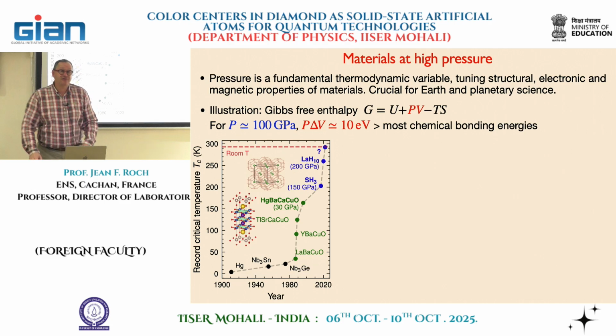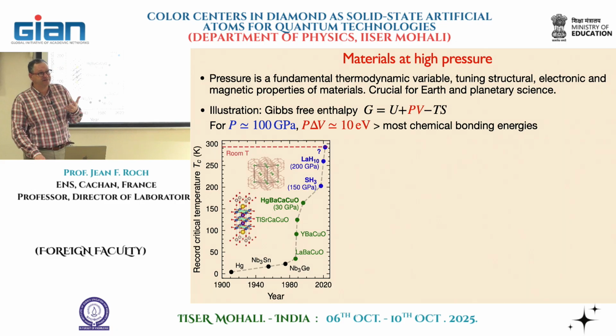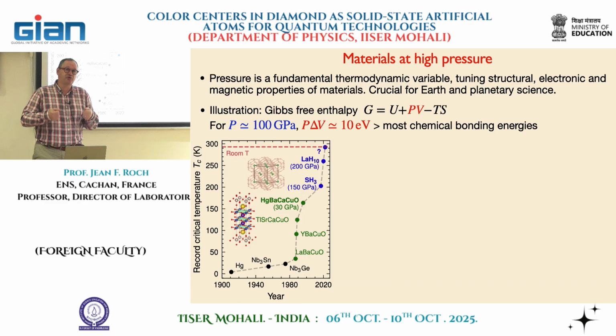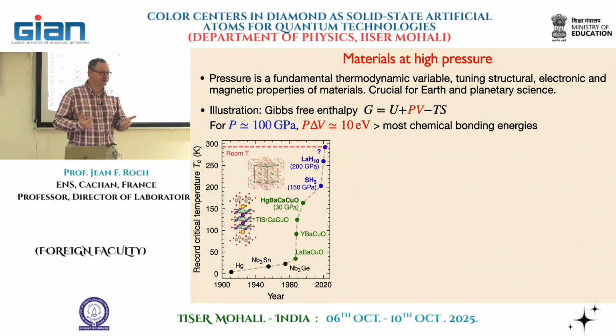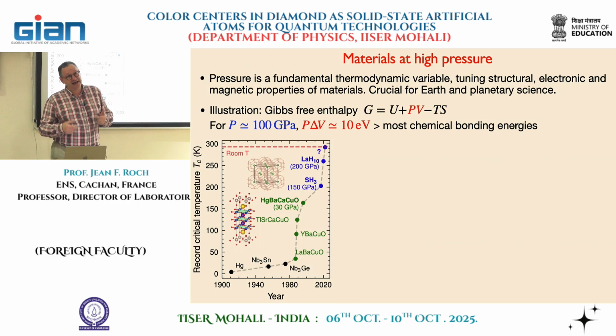That's one point. And then there was another breakthrough, which is now still under strong debate, which is a new family of materials. BCS theory tells you that superconductivity will be far improved if you could have very light material. And then you can think of the lightest atom you can have. It's hydrogen. And following this idea, Neil Ashcroft proposed that hydrogen would be a superconductor, but at pressures where first it is metallic. And metallic hydrogen was expected to occur at amazing pressure.